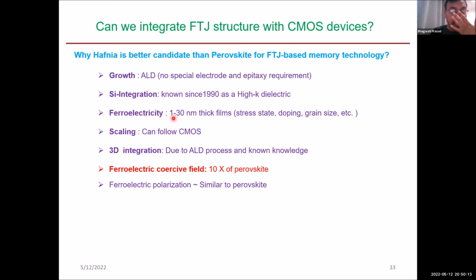And even recently Sayeef Salahuddin's group from Berkeley has shown that you can achieve ferroelectricity all the way down to 1 monolayer of zirconium oxide. So scaling follows CMOS, and you can have 3D integration because it's ALD compatible. The only problem is the coercive field, and that can be worked out if you have some doping and find the right systems. And in terms of the polarization, it is similar to perovskites.